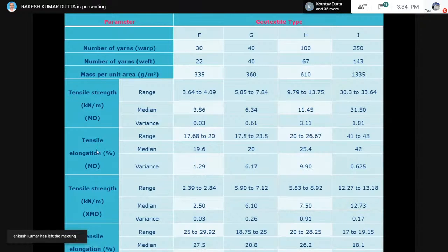Similarly, you see the tensile elongation. Variation was 17.68 to 20% for the first material, 17.5 to 23.5% for the second material. For the third material, it was 20 to 26.67. For the fourth material, it was between 41 to 43. So the median value is taken as 42, here it is taken as 25.4, 20, 19.6. And the variance is again within 10%.